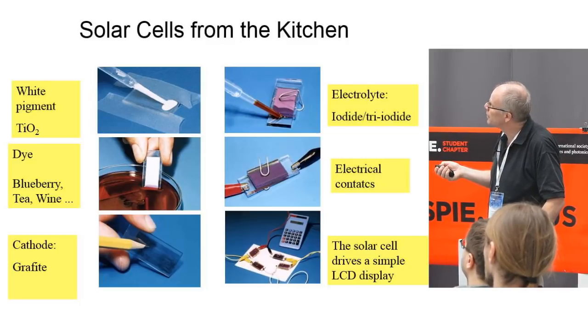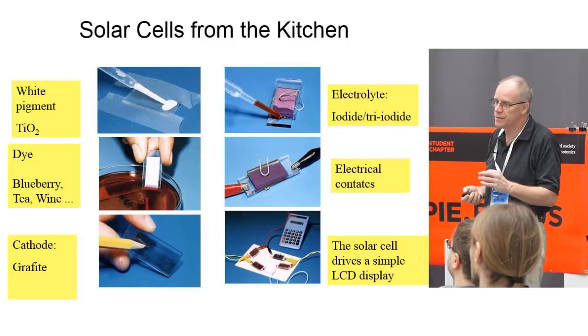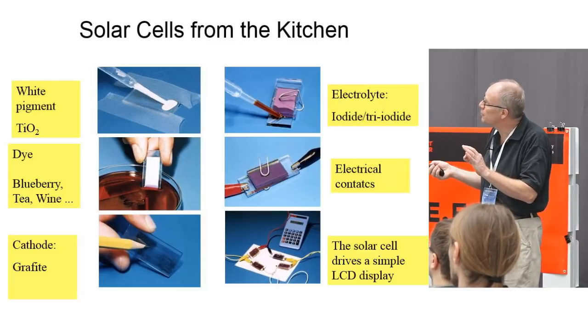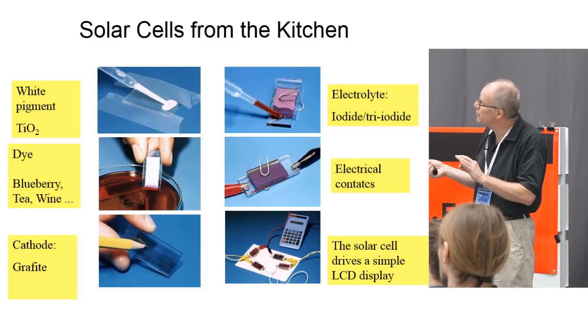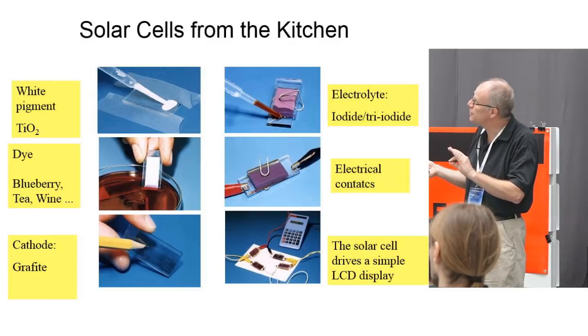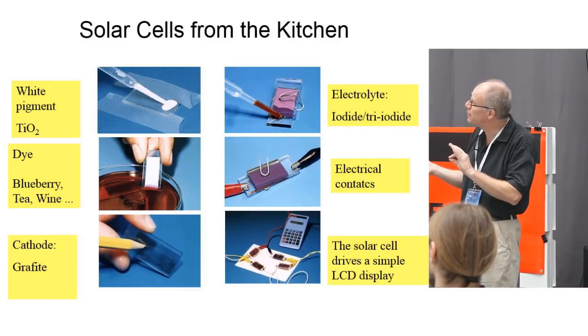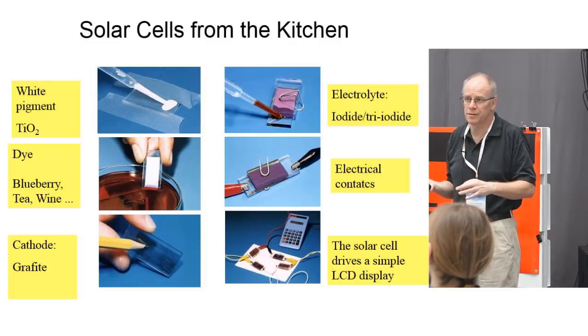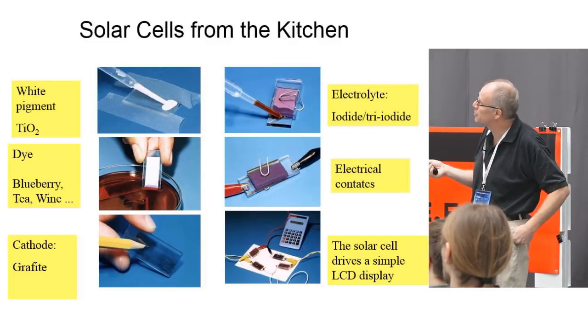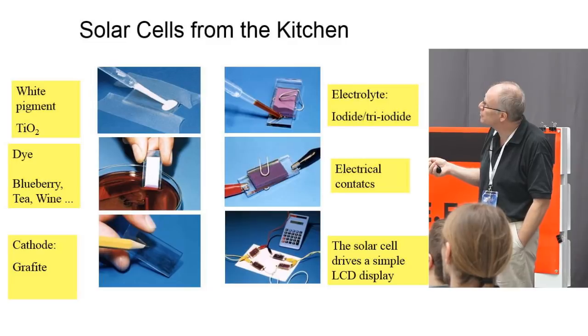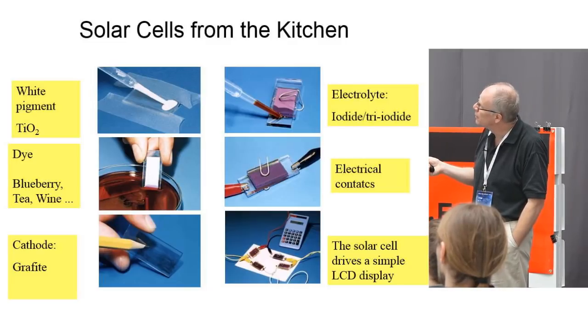You put the Scotch tape on the side here for two reasons. One is that you spread out this titanium dioxide solution, and you want a certain thickness of it. So one Scotch tape is a 5 micrometer thick TiO2 layer, 2 Scotch tapes 10 micrometer, and so on. So normally you take 1 Scotch tape. Then you deposit your slurry of the TiO2